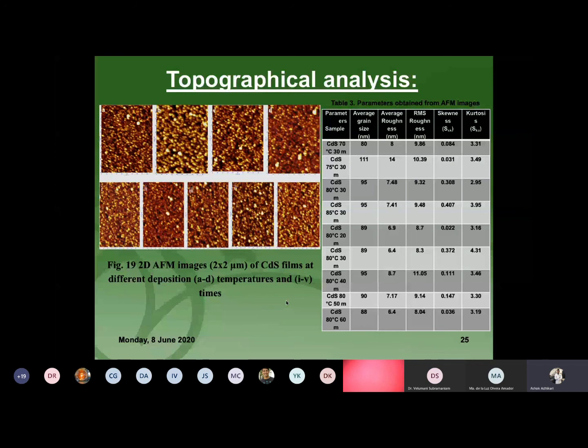We calculated the roughness of the film, which is low, 6 to 14 nanometers, meaning the film is very smooth and symmetrically distributed. This is observed from table 3.